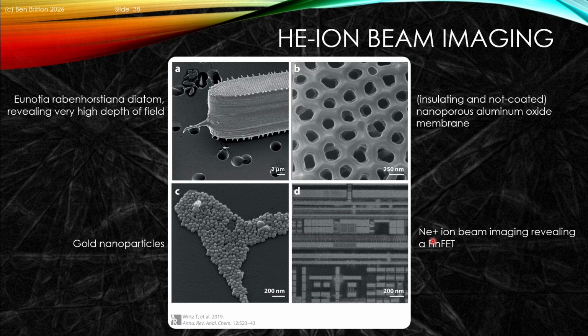Helium ion imaging also has some really nice other bits and pieces to it. It has a very high depth of field because of the size of the source probe, etc. And so we can get some quite beautiful, very, very high spatial resolution images. This is beautiful for looking at a diatom. This is also useful for looking at insulating and non-conductive samples. You can also look at a FinFET, a semiconductor system, with very high spatial resolution, and you can look at gold nanoparticles with, for a scanning ion instrument, amazing resolution without having to go to the TEM in this case.